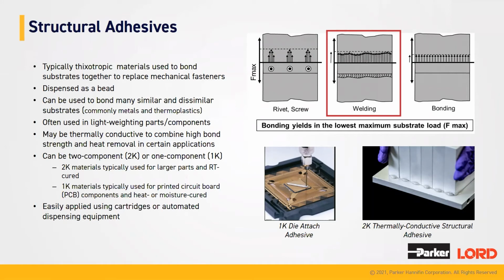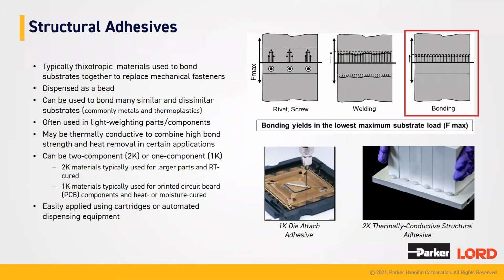Moving to welding, you can see that the overall force is slightly lower, but it's still not completely even across the whole welding line. And finally, moving to adhesives or the bonding picture in the top right, you can see that the ultimate force is lowest amongst the entire bond line, and it's completely even throughout, which is a benefit to adhesives over these other two types of fastening because it provides less force and it's going to be more even force, ultimately leading to better lifetime and reliability of this component.